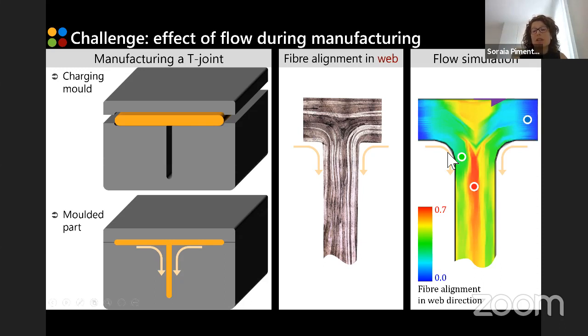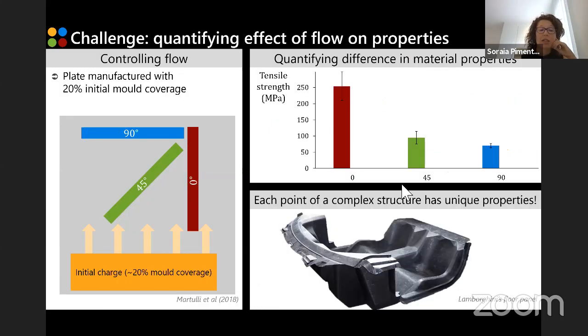Now you can see here that I have highlighted points in red, blue, and green. And because these points have locally different orientations of the fibers, they are going to have locally very different properties. We have quantified this effect, so that can basically be done by making a plate where you control the amount of flow that you have, and then selecting the material from where you test your mechanical properties according to that flow. And you can see here on the right-hand side that indeed we do get properties that are significantly affected by the flow. And what that means is that at each point of your structure, you are going to have different properties of the material. So effectively a different material from a design point of view, that you need to take into account when you are designing your parts.